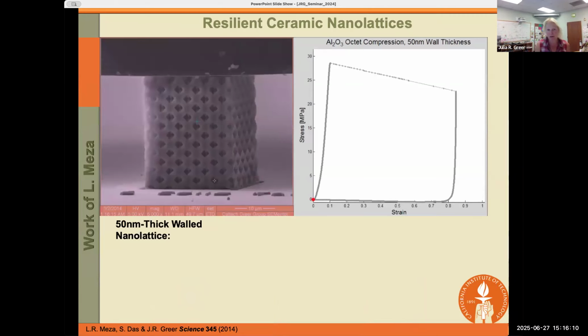So let's get back to our hypothesis. And the hypothesis was, can we utilize the size effect and then proliferate it into materials with larger dimensions by utilizing this concept of architecture? So what I'm showing you here is an octet nanolattice that's made out entirely of alumina. So I imagine many of you are familiar with ALD, atomic layer deposition, right? And so when we talk to our friends who are the ALD experts, they said, oh yeah, we can deposit conformally anything you want as long as it's alumina. So here's the alumina nanolattice. Now the wall thickness here is 50 nanometers, and it's very brittle, right? Most of us know that alumina is a type of ceramic, and it's very brittle.